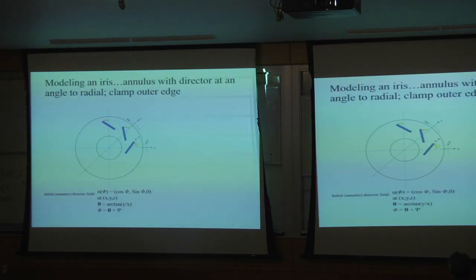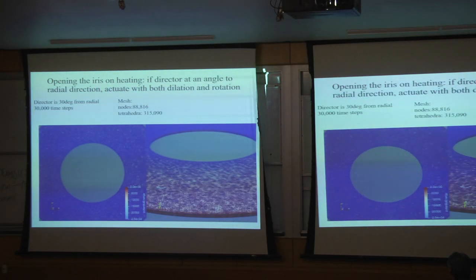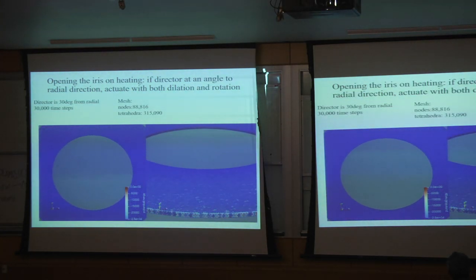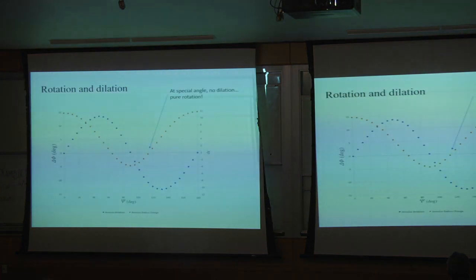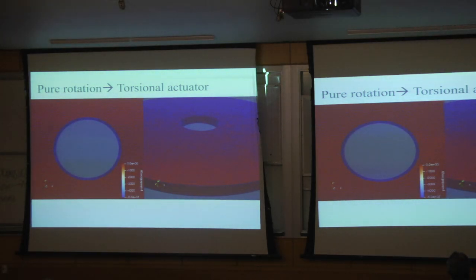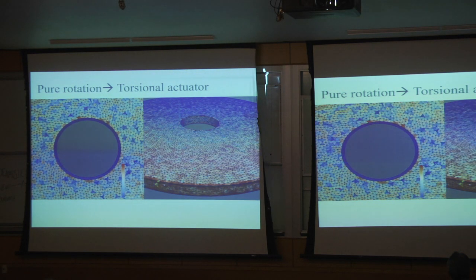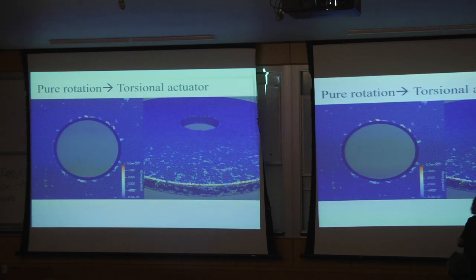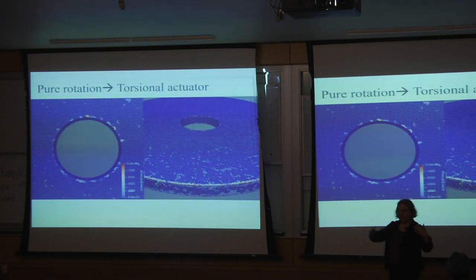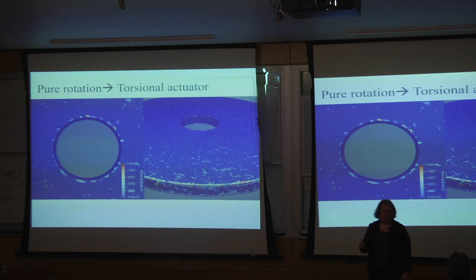And again, we can make it not even pure radial. We can do different angles. So here's one opening. And at a typical angle, you would get both a radius change and a rotation. But we actually found one particular combination of parameters where we could get a pure rotational actuation. So this would be a way we could rotate something. You can have an actuator that actually rotates without changing the shape of the annulus too much. So it's just, again, a fancy actuator that can do different things.